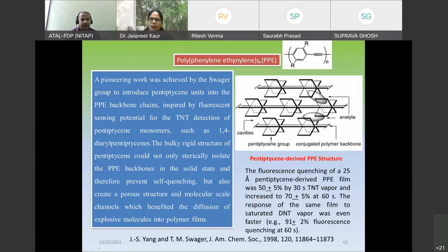So this is the PPE. Normally PPE compounds have a disadvantage because they are not sterically very well isolated, so they can lead to self-quenching. To avoid this self-quenching, Swager and group introduced iptycene units into the polymer structures. Because of this iptycene, they give a bulky and rigid structure. So now this self-quenching phenomenon will not occur, and this will lead to better fluorescence properties.